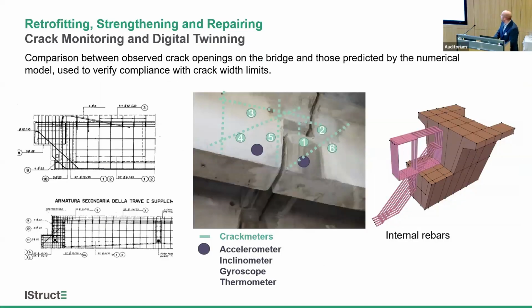And this is another example of a half joint, but this time in a live bridge. The monitors here included accelerometers, inclinometers, gyroscopes, and a thermometer. And the movements of the cracks were monitored in real time, and the trends of the crack opening and closing were reviewed in conjunction with some numerical modeling of the half joint. And this together was used to demonstrate that the crack width limits were met and the observed cracks were within compliance. I believe this kind of method is becoming more common in bridges. It's not really used in buildings.